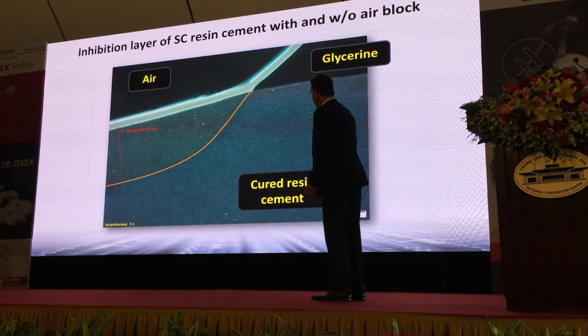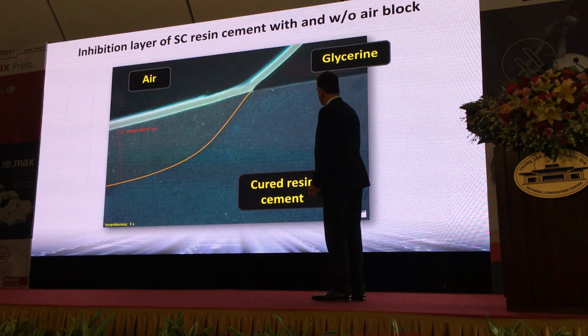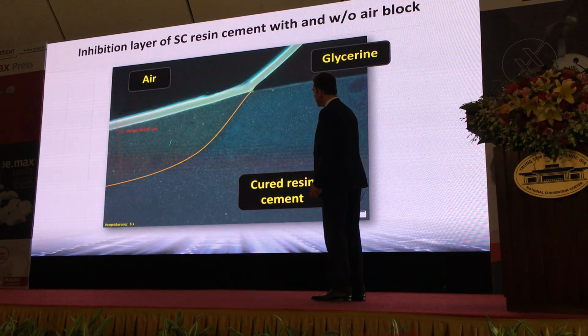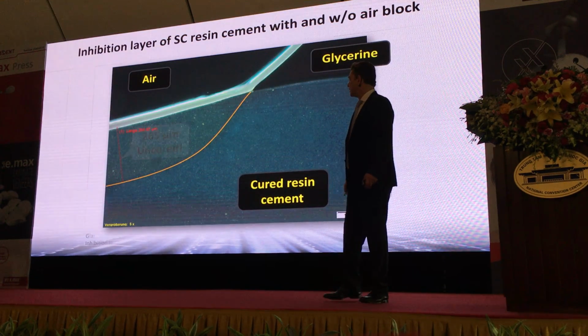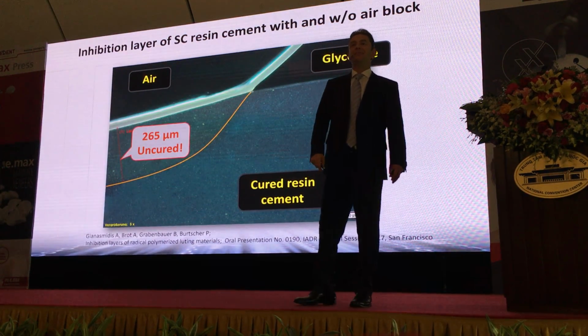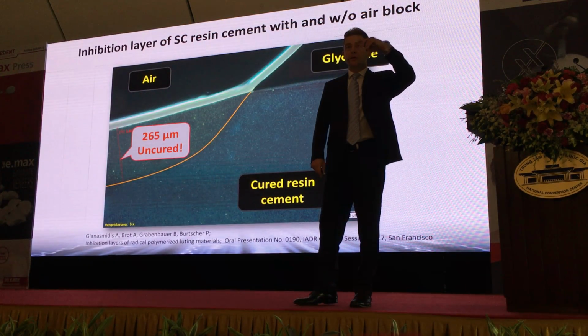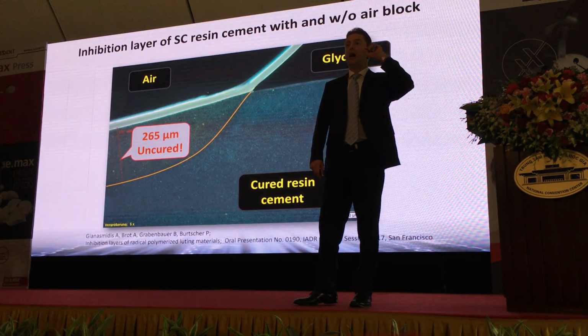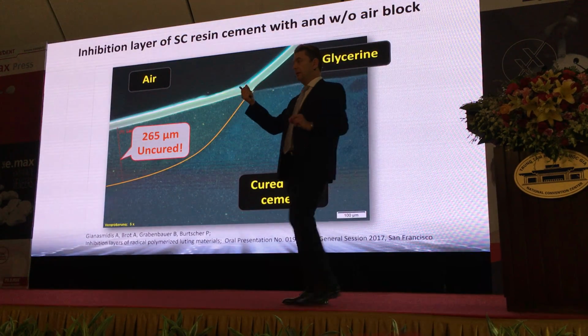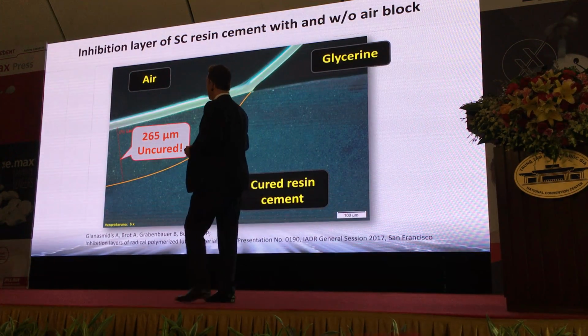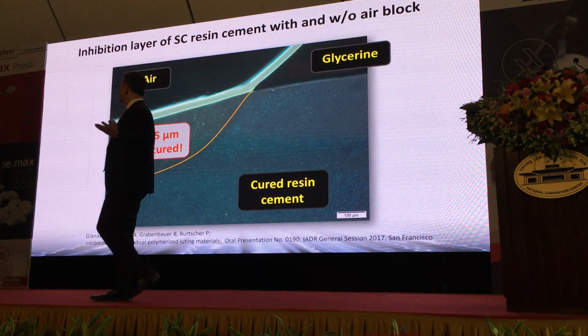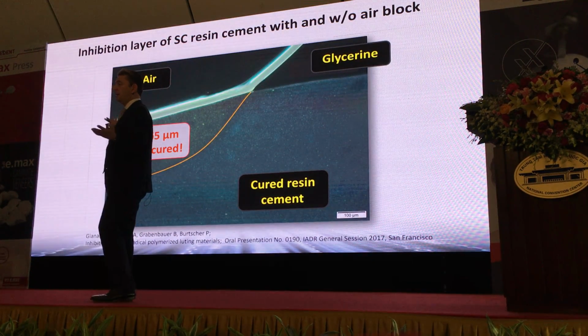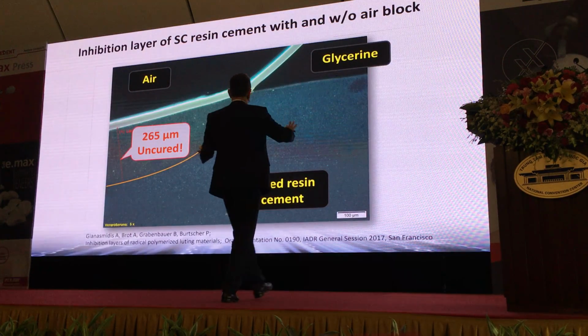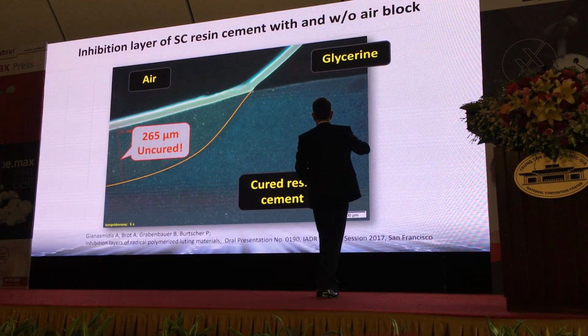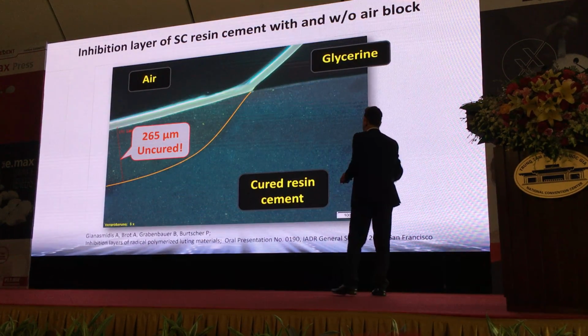Okay, now all this area, this is a cement, a self-curing cement. If you are in contact with air, this is not completely polymerized. So you're looking at about 265 microns of thickness, which is not hard. It's only greasy. Yeah? So if this happens on your margin, that's no good, because this is not stable. It will wear off. Yeah? That's why we need to cover with glycerine, because with glycerine everything is polymerized, everything is hard.